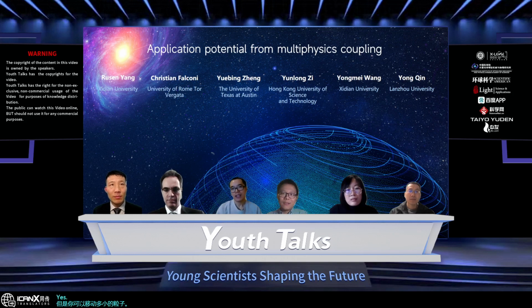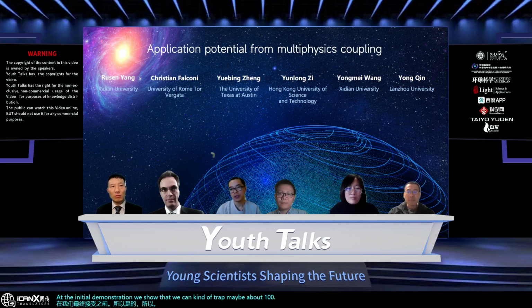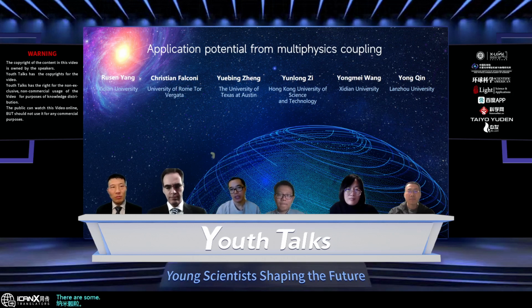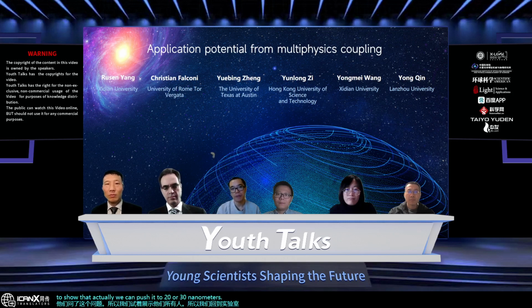Yes, that's the exact question we received from the reviewers for our Nature Photonics paper before it was finally accepted. In the initial demonstration, we showed that we can trap maybe about 100 nanometer particles, but they asked the question, so we went back to the lab to show that we can push it to 20 or 30 nanometer, and we can push further. Theoretically, we can trap any type of small particles.